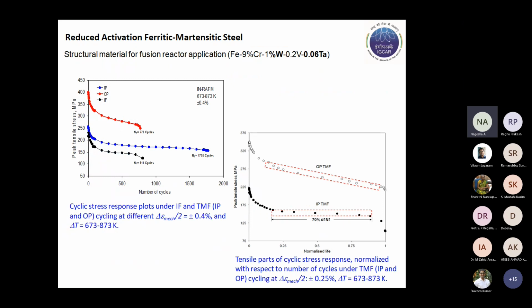And another material was also investigated. It is referred to as reduced activation ferritic martensitic steel. It is a slight modification of the 9 chrome 1 moly type of steel, where molybdenum is replaced with tungsten, and niobium is replaced with tantalum, because this is a structural material for fusion reactor application, for the test blanket module and the first wall, the plasma facing component of the fusion plant.